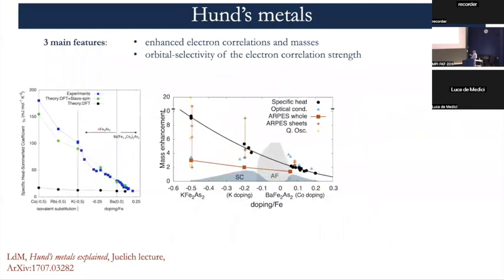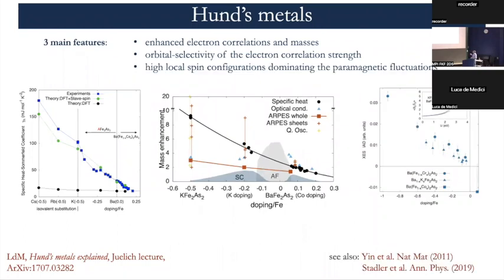And the third characteristic, which then is one of the three main features of Hund's metals, is the fact that all this is due to local moments in the paramagnetic phase, so fluctuating local moments, growing when you go towards half filling, and these are constraining the physics in a way that it becomes more correlated and more selective the more you move towards half filling. Now, my second spin-off: one might be tempted to say, okay, what happens if I go even closer to half filling? And is it possible?